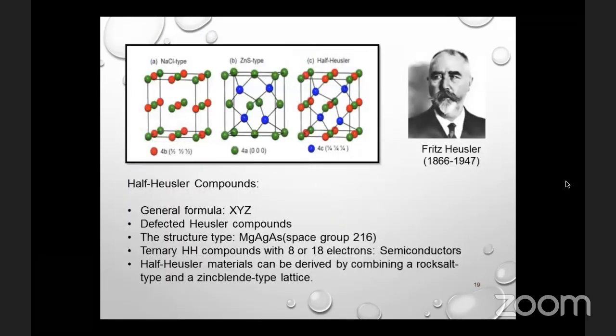If we would like to take a more detailed look at the structure of half-Heusler material, you can see here. Half-Heusler material can be derived by combining rock salt and zinc blende type structure. The structure of this material is magnesium silver arsenic type, cubic in space group 216.